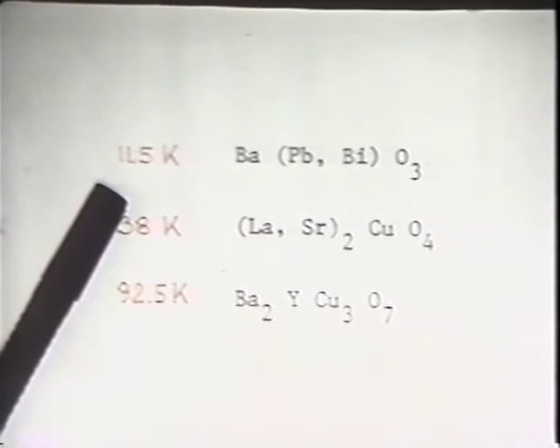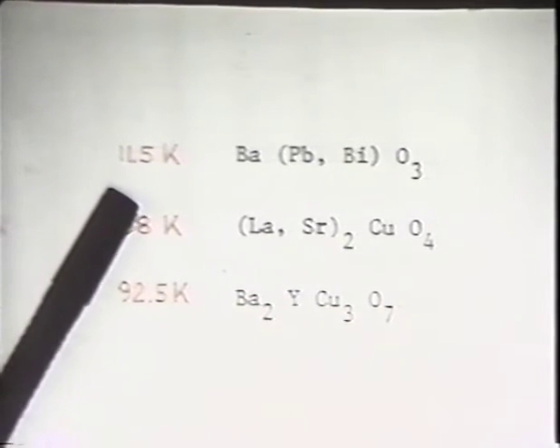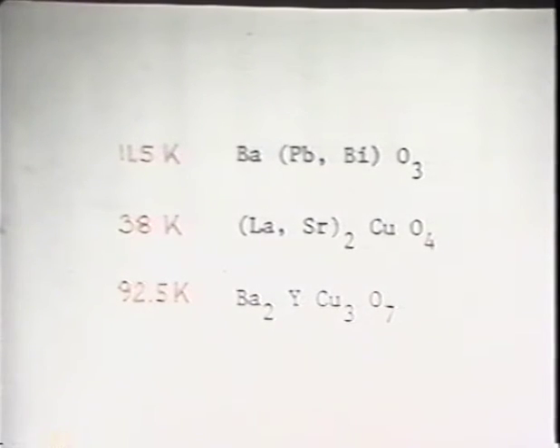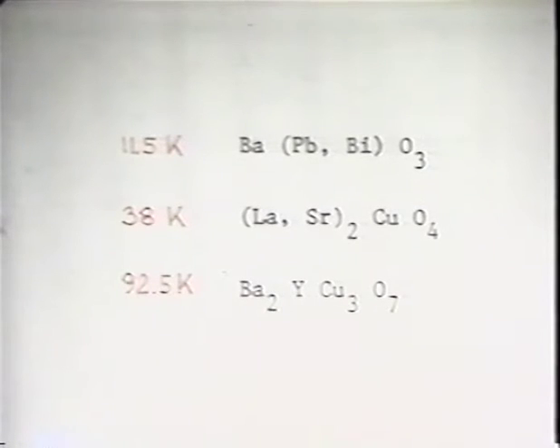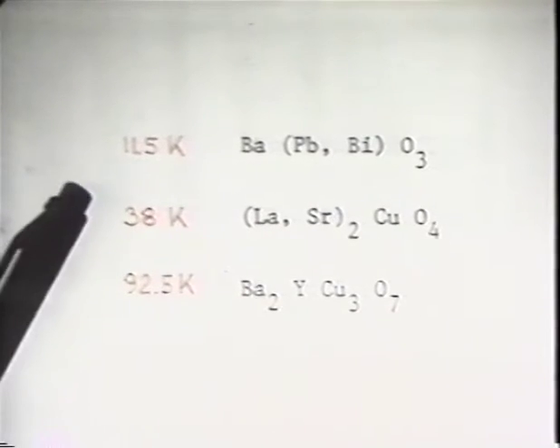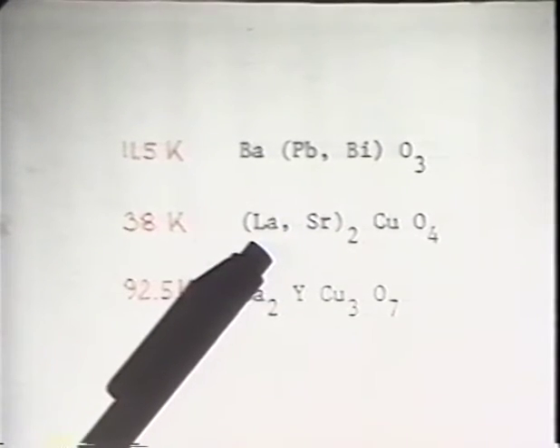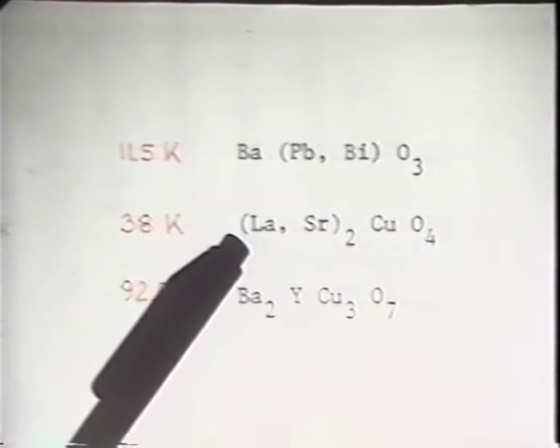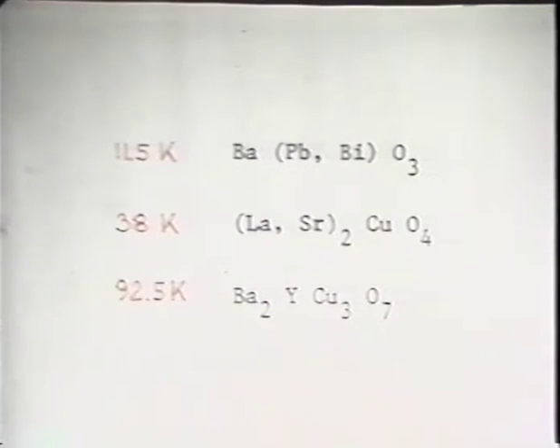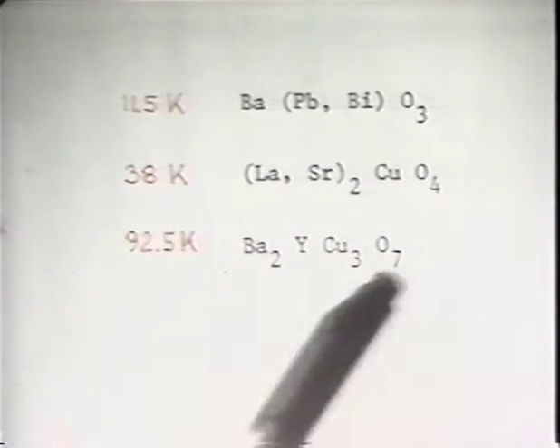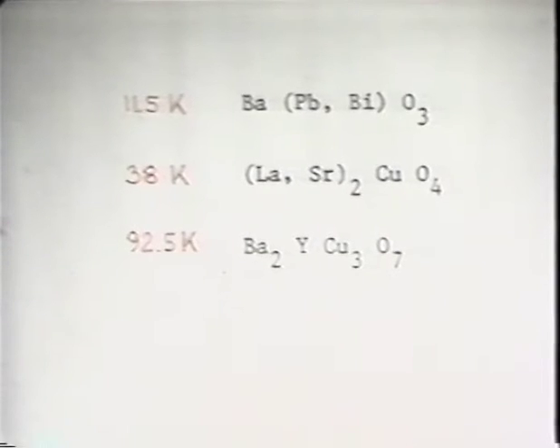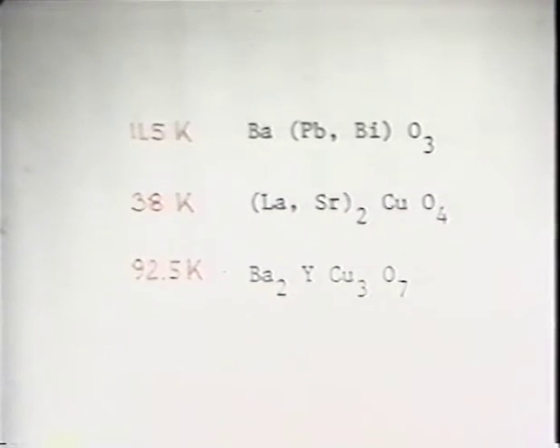Superconductivity research in oxides goes back quite a few years. As Professor Mueller has pointed out, we have been working on this. We started working on barium lead bismuth oxide five to six years ago, and through our work on very high quality single crystals, we gained lots of insight about these oxide superconductors. Then in the last three months, through substitution of strontium in the lanthanum barium copper oxide, TC was raised to 38 degrees. Finally, I would like to concentrate on the latest compound because it has the highest TC, and also because we don't have much time to talk about the other ones.